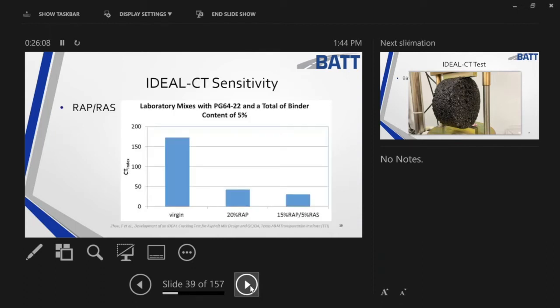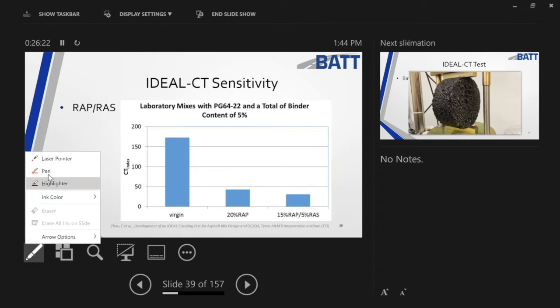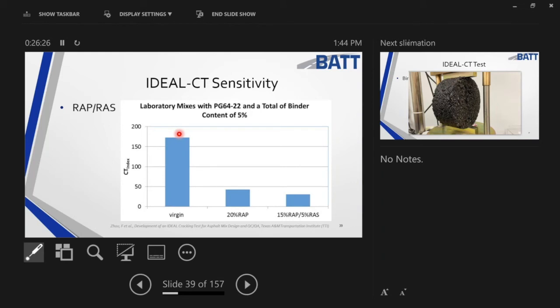And here, this is just showing you sensitivity to the ideal CT. And what Fuji did here is he took laboratory mixes, and aging is important. And I'm gonna say a couple of things on aging here. Fuji did 4-hour aging on everything that he has done. And the reason the aging is important, aging not only allows absorption of the asphalt into the aggregate,